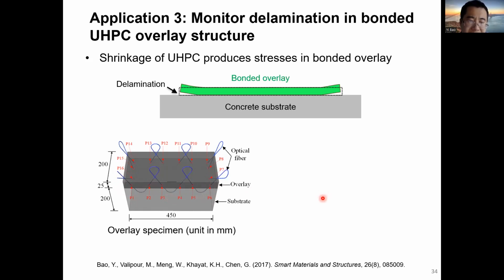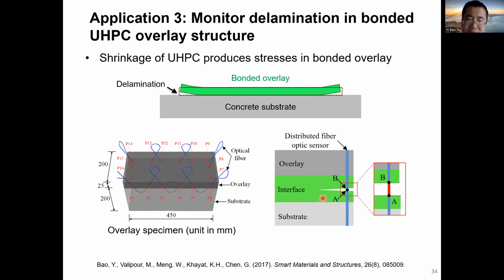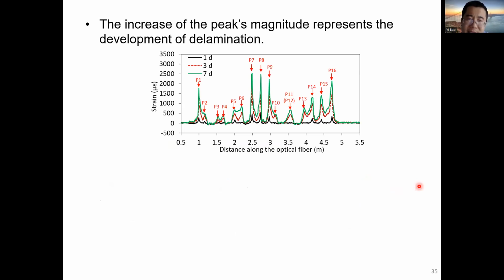intersection points. And at each intersection point, if delamination happens, for example, at this point, before delamination, this point is one point, A and B. And after delamination, this point is separated into point A and point B. And the fiber optic cable at this position will be stretched to a higher strain level. And therefore, we could detect some peaks in the measured strain distribution.